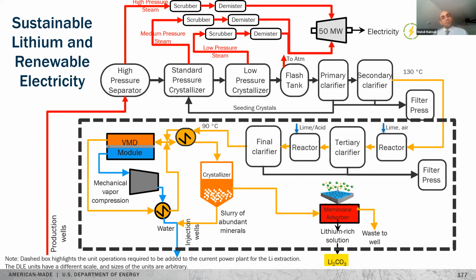So then when we get to the certain point, we will send it to this heat integration to the crystallizer. And some of the crystals, some of the salts which will crystallize in the crystallizer, and the slurry of those abundant minerals are going to be mixed with water and sent back to the geothermal well. So the product of this is at lower salinity, and it's being sent to the membrane adsorber for selective removal of the lithium. Essentially, this is how we are going to deal with all those precipitations and silica, iron, some of the transition metals that are essentially making most of the technologies almost unfeasible because of their scaling and precipitation.